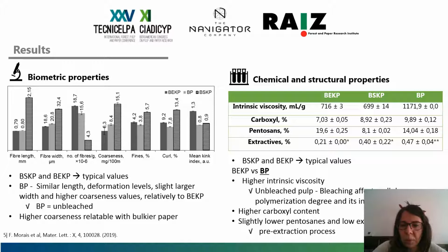Also, this pulp revealed a higher carboxyl content when compared with the eucalyptus pulp, and it also revealed slightly lower values of pentosans and extractives, which was relatable with the fact that we used a pre-extraction process for its production that removed most of the extractives alongside with some sugars.